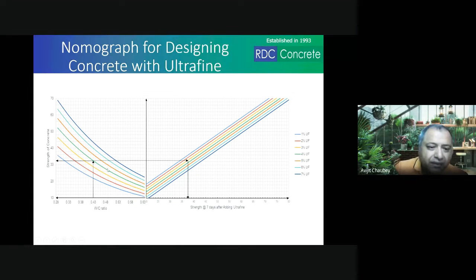So your graph is actually the green one. Your current materials are behaving like the green one. And now you want to increase the strength to maybe 38. What you do is, from the same point at 0.43 water cement ratio, you plot a line till you come across 38 MPa or whatever strength you want. The point where this intersects is the line of percentage of ultrafine that you need to use. So at 0.43 water cement ratio and 3% ultrafine with the same set of materials, instead of 32 MPa, you will end up getting 37, 38 MPa.